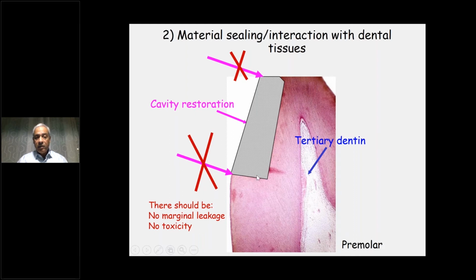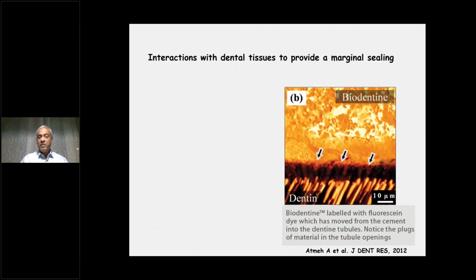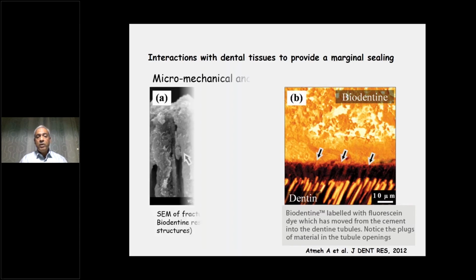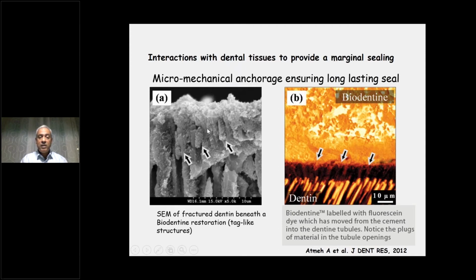Regarding the marginal sealing of the material, which can be applied without any preparation of the dentin surface, there was a study done at King's College where the authors mixed the material with a fluorescent dye. And what you see is that the fluorescent dye penetrates in the dentin tubules. This was impressive, which means that the dye penetrates into the tubules, producing kind of plugs into these openings. And when you look at this by scanning electron microscopy, you see that there are some plugs in the dentin tubules, and this allows a micromechanical anchorage, ensuring a long-lasting seal.